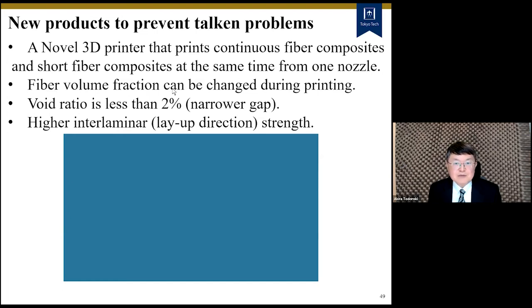And the fiber volume fraction can be changed during printing. Markforged cannot change it. And the void ratio is less than 2%. In the Markforged, the void ratio is still 7%. And the interlaminar strengths are higher, I mean the layer projections. This video showed the